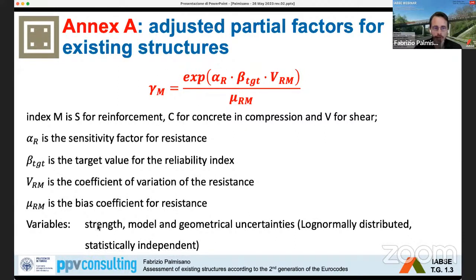The variables involved are strength, model, and geometrical uncertainty, and the general assumption is that they are log-normal distributed and statistically independent. And this formulation is a function of the sensitivity factor for resistance, the target value for the reliability index, the coefficient of variation of resistance, and a general bias coefficient for resistance, that is the product of the bias of each parameter involved. I don't have time to go further into details, but I want to mention that all the details on the procedure included in the Eurocode will be given in the next webinar on the 9th of June, with an application to a real case study.